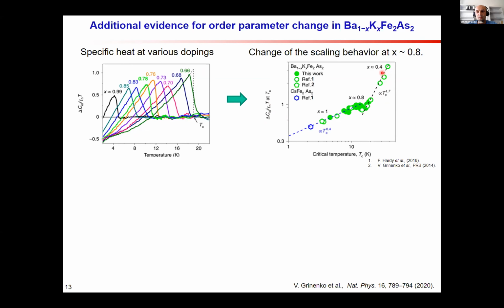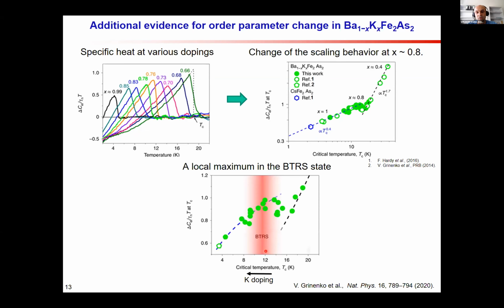At low doping levels is the well-known scaling behavior where this value varies roughly like TC squared, the so-called Bud'ko-Ni-Canfield scaling, which holds for many iron pnictides and is related to unconventional S+- superconductivity. On the other hand, at higher doping level we observed another scaling behavior, which also indicates unconventional superconductivity in the system, and could be understood in terms of S+- superconductivity also, but since there is a very big difference between the two scaling behaviors, we expect that it's another type of S+- superconductivity. And this state with broken time reversal symmetry is exactly observed in the region where the scaling changed from one to another.